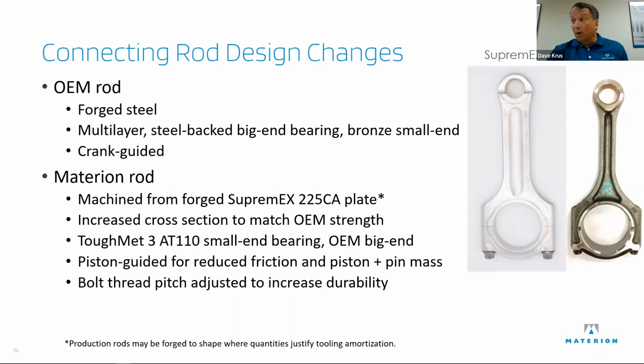It is thicker. You hear the two parts there. It looks more like a titanium rod than a steel rod. And there's a ToughMet bearing in there. You can also see this maybe a little bit easier on the photo to the right, that it's thinner at the top for the piston guiding. And one of the things that Cosworth did, just to be careful, because like titanium, it's a little more notch sensitive than the steel, they were a little bit worried about the bolt thread pitch in the threads. They adjusted those to increase the durability.